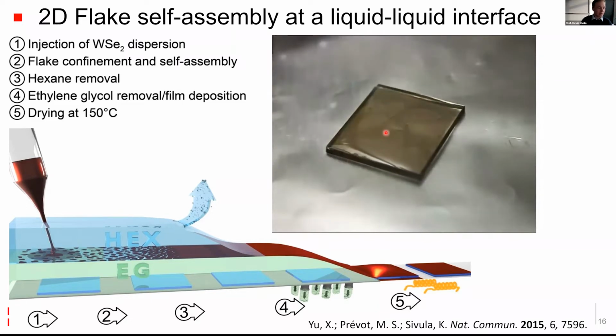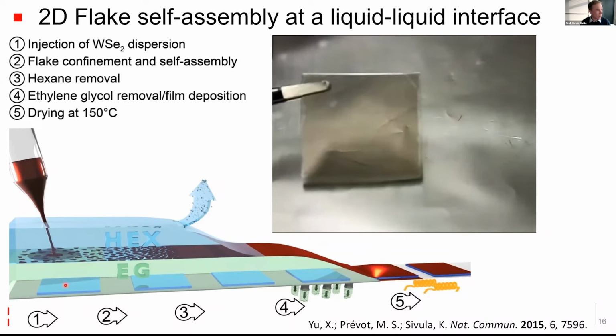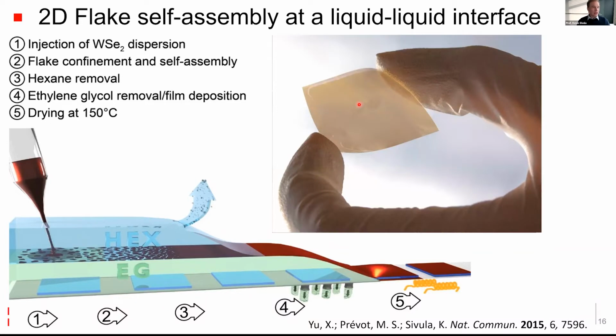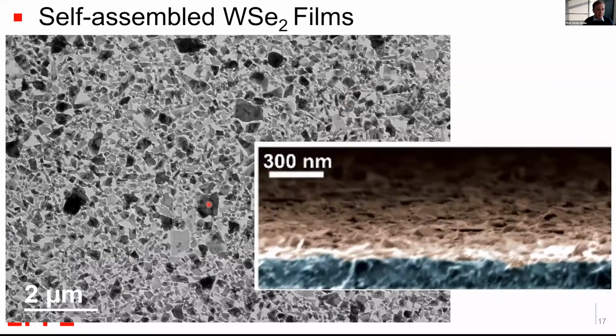Simply heat it briefly to evaporate the rest of the solvent, which can be ethylene glycol or water, and we're left with this nice nanoparticle film on the substrate. We can do this on flexible substrates. We can do this over relatively large areas, which I'll show you later. But the most important thing is that our flakes have a good contact with our substrate. As shown here in this cross-sectional SEM image, our nanoflakes of tungsten diselenide are all in good contact.